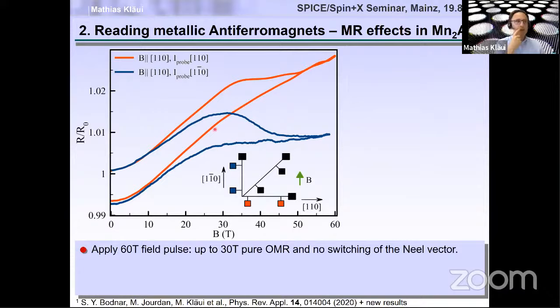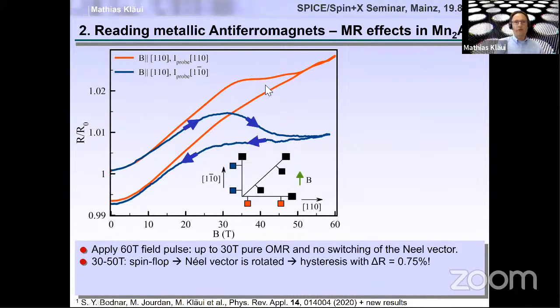So we see that if we apply a field, we can measure during the application of the field pulse, and we can see that the resistance firstly goes generally up. This is a typical ordinary magnetoresistance effect, so there's nothing particularly magnetic about it. That's something that all materials do. But you can also see that above this field, roughly here, we see a hysteretic change of the resistance, and that is assigned to a change of the Néel vector orientation. So that's this area here.